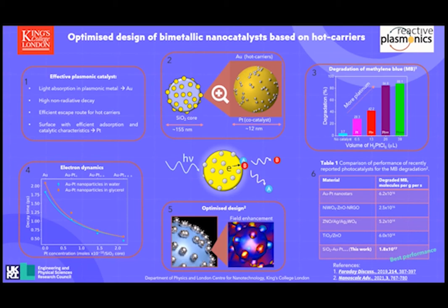Here, we studied heterostructures consisting of silica cores decorated with gold nanoparticles, which are coated with platinum. Gold is a plasmonic material that provides the hot carriers, and platinum is a co-catalyst that facilitates surface adsorption. The catalytic efficiency was studied as a function of quantity of gold and platinum by varying the size of gold particles and the loading of platinum on the surface of gold.